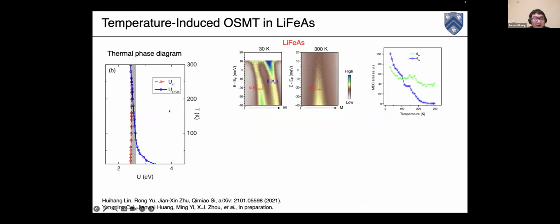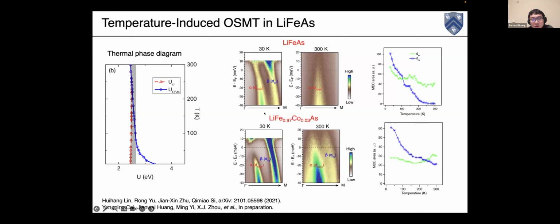There has been a prediction by Rong Yu, Jian-Xin Zhu and their colleagues that lithium iron arsenide is in a temperature-induced orbital selective Mott phase, but we noticed that this orbital selective Mott transition is very sensitive to the Coulomb interactions. If we slightly decrease the Coulomb interaction, this whole compound can enter a phase without the temperature-induced orbital selective Mott transition. This is actually the case we found in slightly cobalt-doped lithium iron arsenide. Even if we increase the temperature up to 300 Kelvin, the dXY orbital spectral weight still exists.